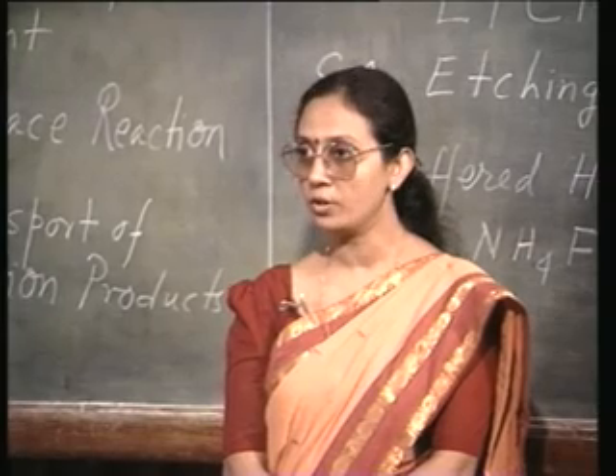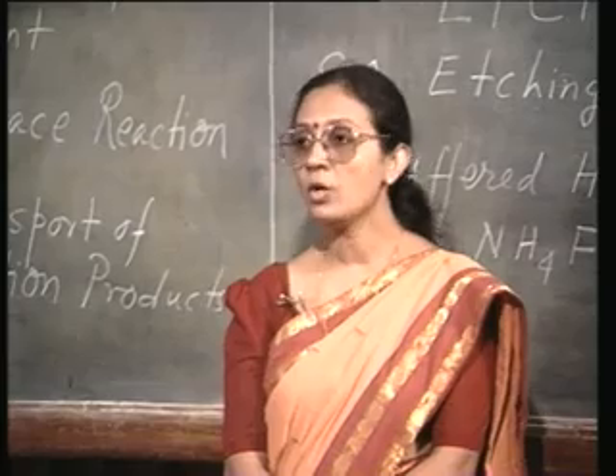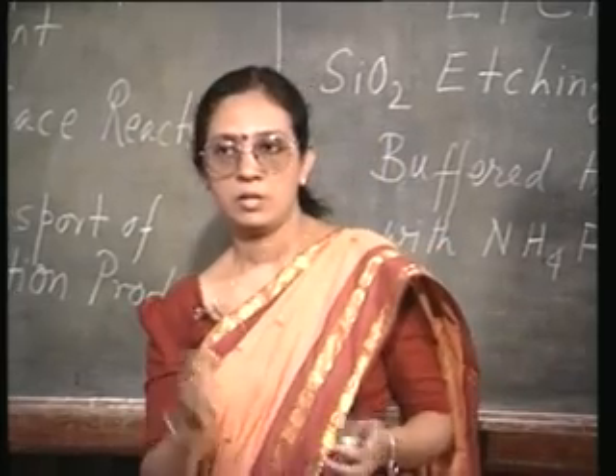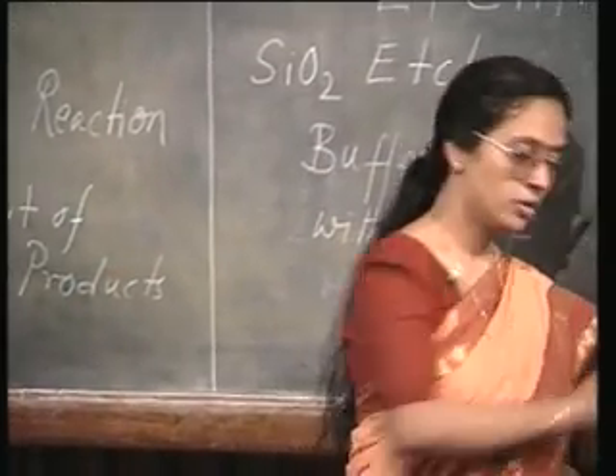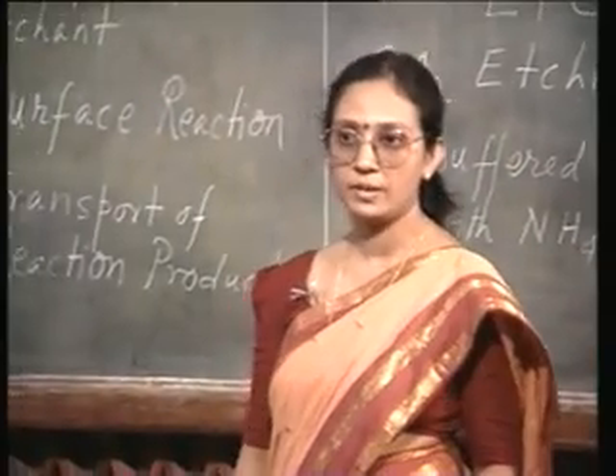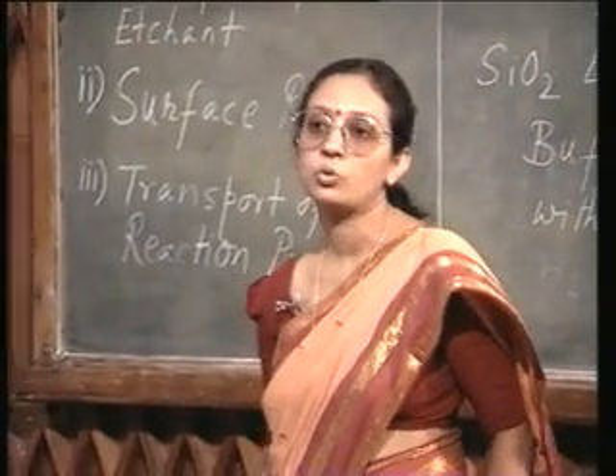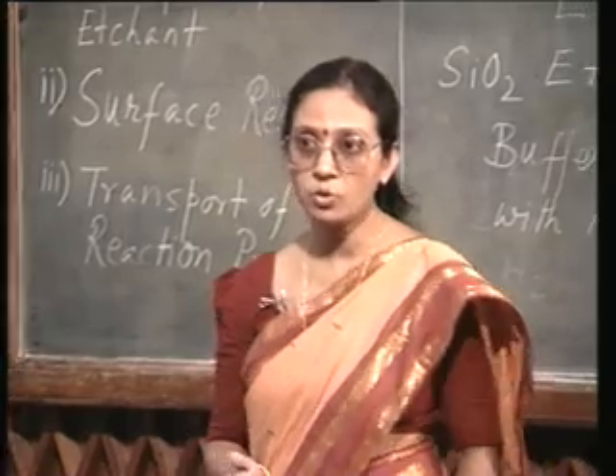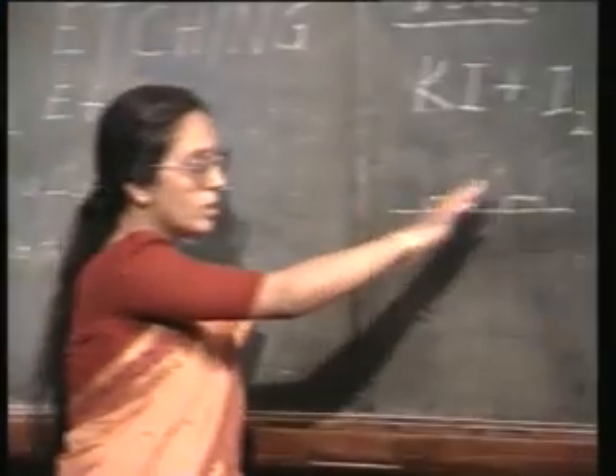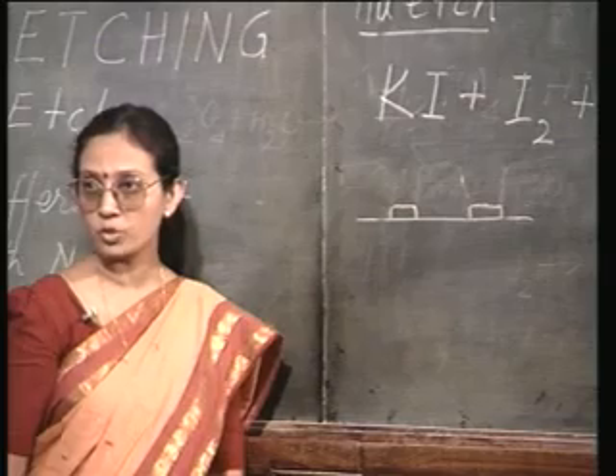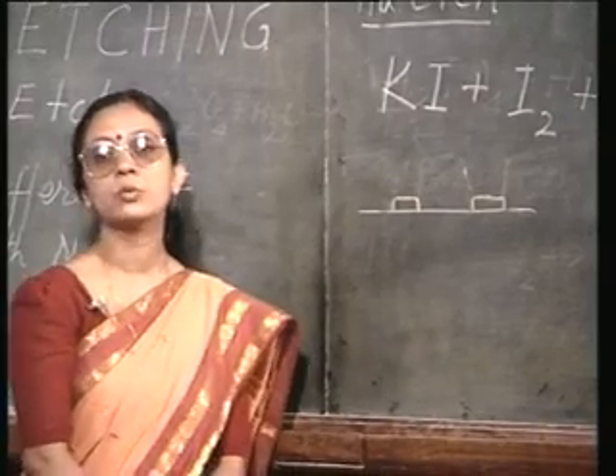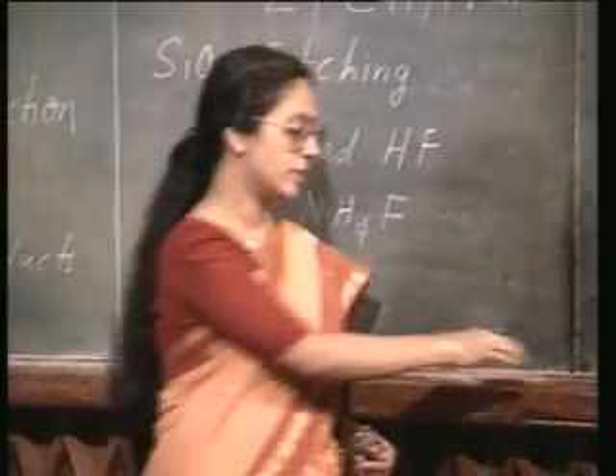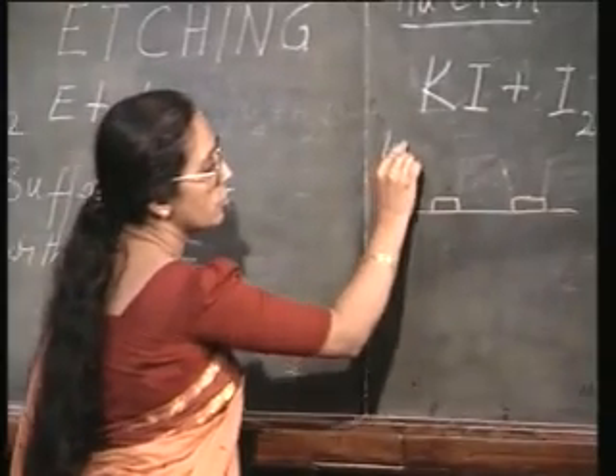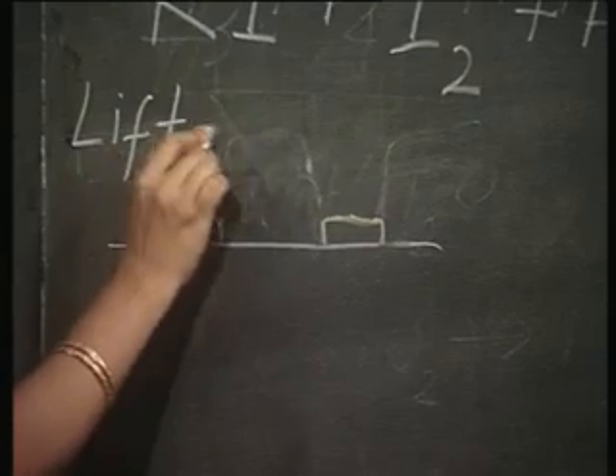So, you see, I did not have to etch gold. Whenever you are having to use gold as a metal, you try not to go for gold etching. That is, you do not want to put gold all over and then etch it from the remaining portion. What you try to do is go for a lift off technique. It is called a lift off technique.